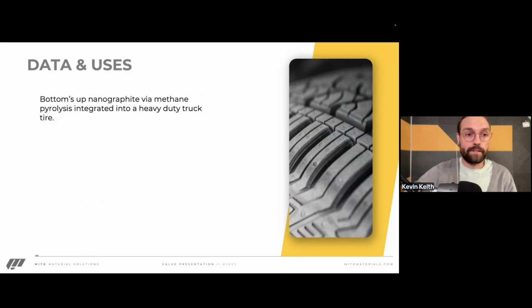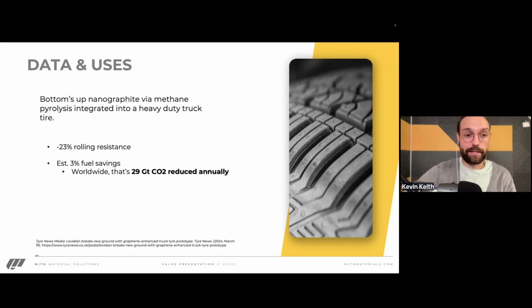Another use case of these bottoms-up graphenes is that this nanographite from methane pyrolysis was integrated into a truck tire, of all things. Tires, as of right now, use carbon black because of its rolling resistance properties and its longevity. Whenever they put this nanographite into this truck tire, they found that it decreased rolling resistance by 23%, which should correlate to an estimated 3% annual fuel saving. To put that in perspective, worldwide, if we were to use these tires, that's 29 gigatons of CO2 reduced annually, before you even factor in the fact that you're cracking the methane and creating this value-added carbon material.